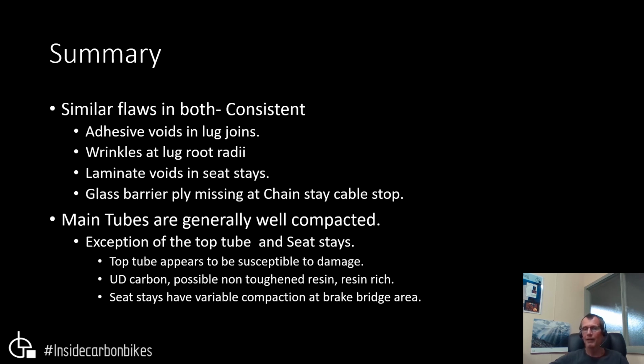So particularly the wrinkle and the void at the head tube lug, that's probably the biggest concern, because even if it hasn't got a huge effect structurally on the bike, and you need to do some actual destructive testing to validate how much of an influence it has on the structural properties of the bike. Regardless of that, nobody wants a big crack right around their head tube down tube junction. Nobody wants to be looking at that when they're riding their bike down a hill at 80 kilometers an hour or 50 mile an hour, or whatever you want to do. You don't want to see a big crack like that. So that is a concern.